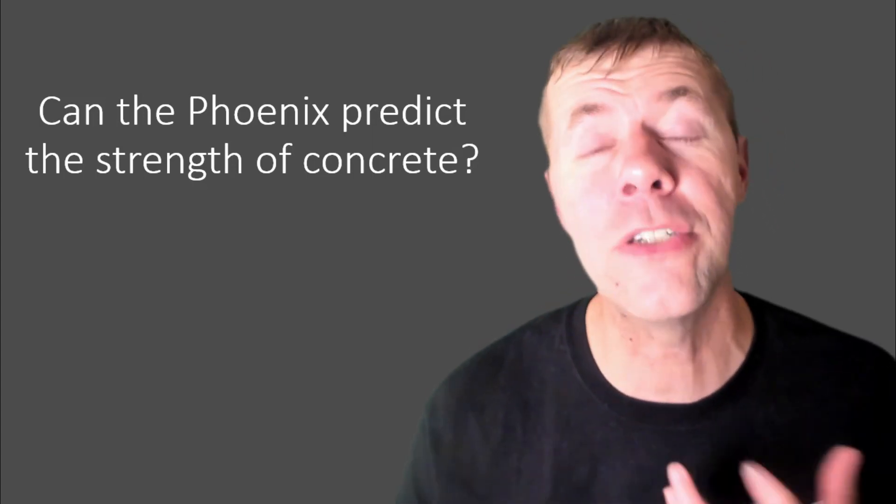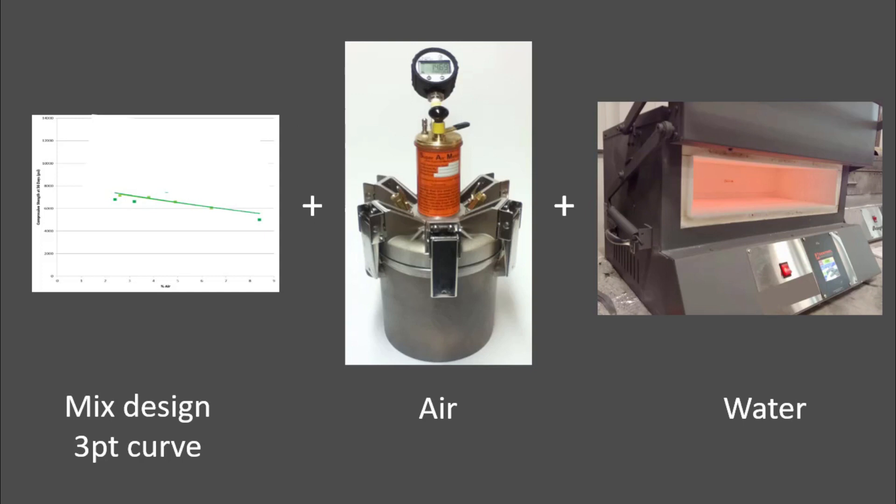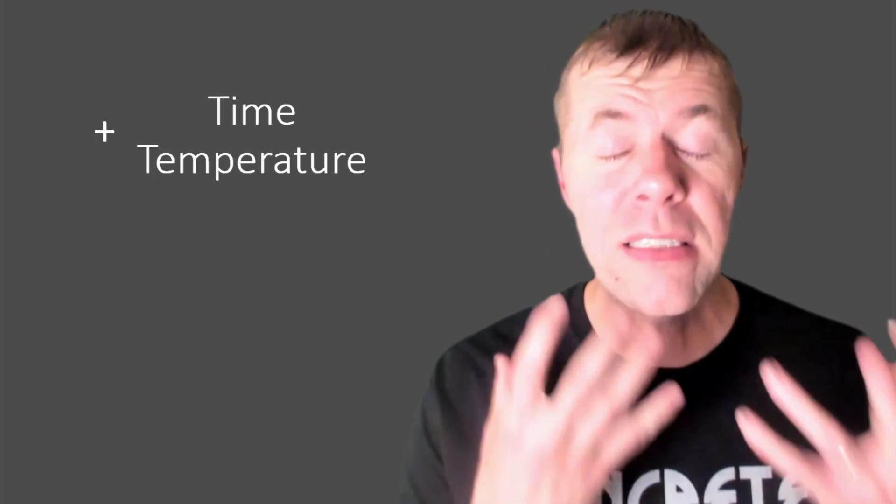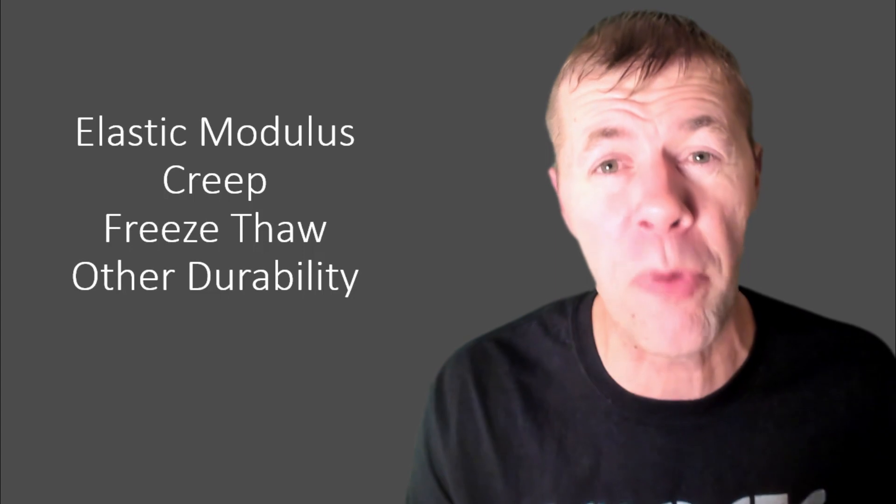Well, kind of. It can contribute to it. For example, if I have a three-point curve from my mix design, that means if I put that together when I was making my mix, and if I have the air content of my concrete mixture in question, if I have my water content of my concrete in question, and if I give it some time and make sure it's hot enough, not like frozen forever, it's got some heat to that mixture, then the strength will come. That means I can predict what my compressive strength is, gonna get that right. I can get flexural strength, no problem. If you're a cuber out there, you break concrete cubes, not a problem. We got that covered as well. We can get elastic modulus, we can get creep, we can get freeze-thaw performance, we can get other durability parameters. Holy cow! That's amazing, right? That's the power of what this tool can give you.